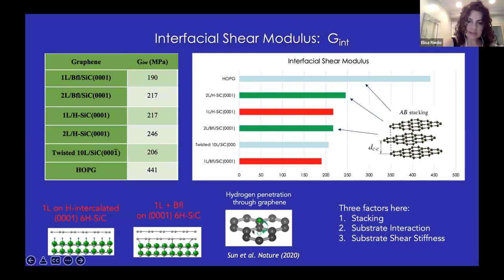We also think that hydrogen could be attached to the top graphene. And so there could be almost like a Velcro type of sliding, which increases even more the shear elasticity. Okay, the other low value is given by twisted 10 layer graphene. And again, we think this is due to the fact that the stacking is really not the preferential stacking. And so the structure is looser.